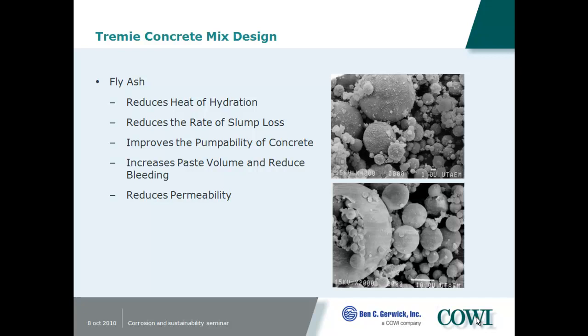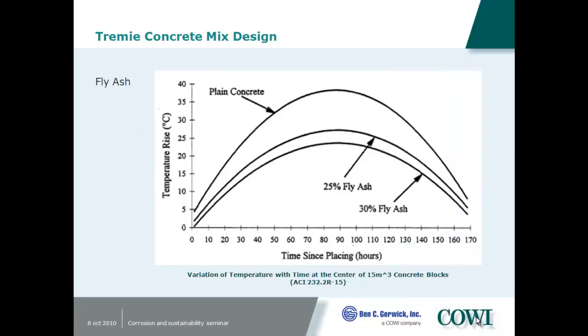So this just gives you some of the background on fly ash. It comes from burning coal, and then they collect the fly ash going up the flue, and then they have to process it a little bit. But it also reduces the heat of hydration. It can reduce the rate of slump loss, so you can have a longer workability life. It can improve the pumpability, decrease the permeability by increasing the paste volume and reduce bleeding. I guess this is a result of some of this hydration going on. So this just gives you the time since placement with the heat rise by using up to 30% fly ash. You can go higher than that, but you get reduced strength gain, as we showed here with our